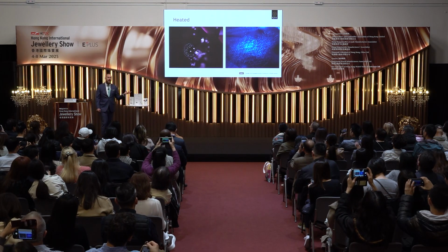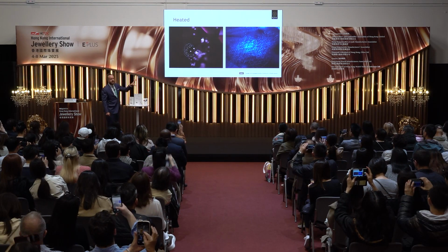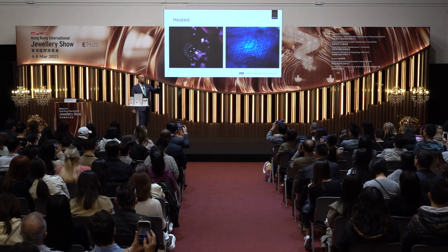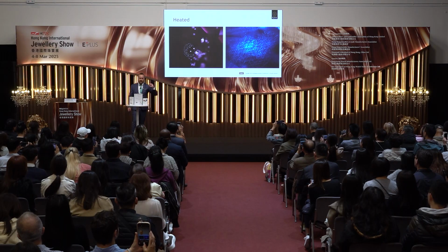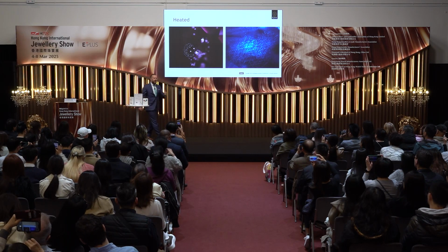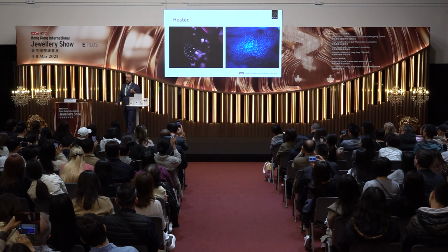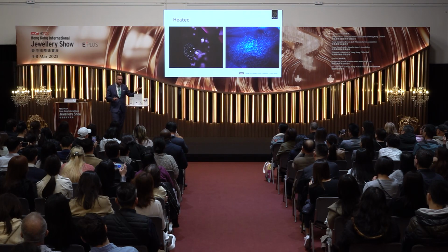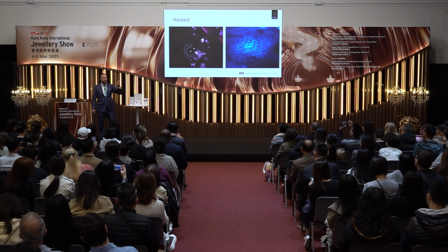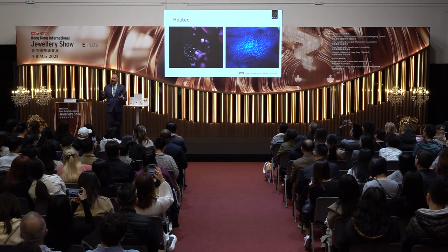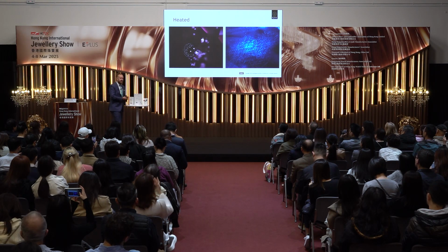Now, detecting that often relies on the inclusions again, where we can see that the inclusions are completely different from what we saw in those untreated stones, because these are very similar inclusions. The inclusions here on the left, we can see they are no longer transparent. They are completely turned frosty, and they are what we call now a snowball inclusion, because they look like these little fluffy white clouds, completely degraded by that high heat that they have been subjected to.